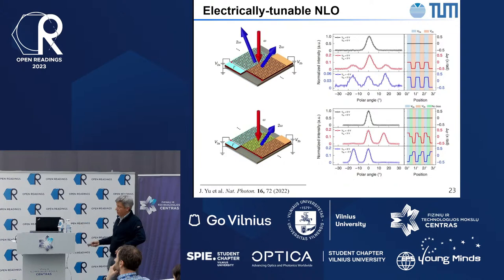If you try this structure, where you put zero bias here and positive bias there, you continuously vary the voltage across these surfaces, because the current basically goes from this contact to that contact, and the voltage continuously varies. In that case, you apply bias voltage, and you see that at zero bias, you had a response of second harmonic at normal incidence. At bias where this is zero and this is some positive value, you have some component of second harmonic generation steer to the left. You reverse the bias, and this same component of second harmonic generation now steers to the right. So you introduce a continuous phase variation.